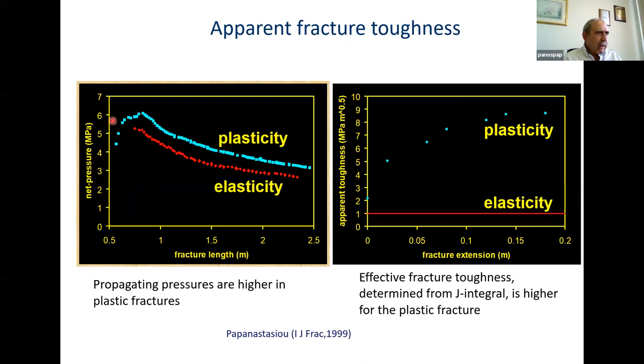Next, I will show the net pressure as the fracture propagates, for elasticity and plasticity. What we can see here is that with plasticity, the net pressure increases at the beginning until the plastic zones are fully developed, and the effective fracture toughness is fully developed at that point, and then decreases like the elastic solution. And here we have the effective or apparent toughness, as we call it, as a function of the fracture extension. It starts by increasing the effective fracture toughness, but it reaches a kind of limit value after some propagation steps. With elasticity, of course, the toughness remains constant.